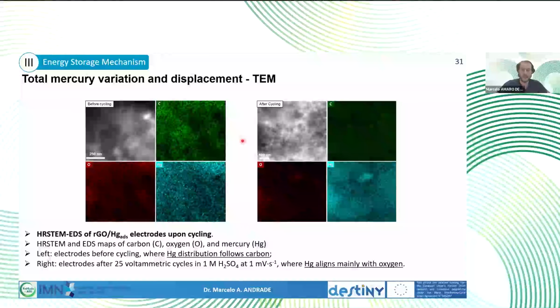And finally, with the Jülich team, we could see on TEM before, on ex situ experiments, so that was before cycling the RGO with mercury electrode, mercury is basically following the position of carbon, as expected, since we saw that later it is mostly physisorbed on the surface of RGO. And then on post-mortem, after cycling, mercury starts following the position of oxygen. And it is possibly due to the irreversible formation of species that are not electroactive anymore, and they migrate throughout cycling.